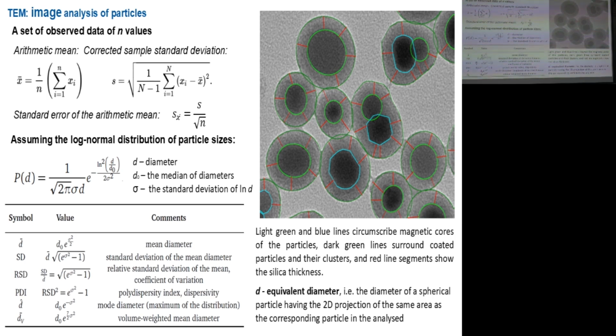And you can collect a large number of values. Then you will calculate some arithmetic mean for the size. It's trivial for spherical particles or for cubes. In case of some random shapes, you may consider measuring the area, quantifying the area, and calculating some equivalent diameter of 2D projection of a hypothetical spherical particle with the same area of the 2D projection. And then you can calculate this equivalent diameter, calculate the arithmetic mean.